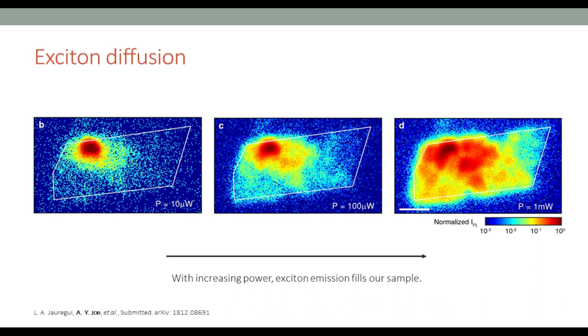We find that most of the photoluminescence is coming from the laser position, which is expected. But as we ramp the power up, we can actually see the entire sample light up. As I said before, this is around a 1 micron spot size, but we're seeing photoluminescence from almost a 10 by 20 micron sample area. This led us to believe that we have diffusion, but we had to do some further studies.